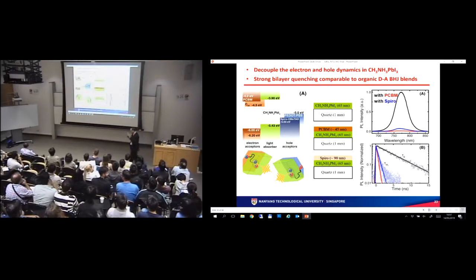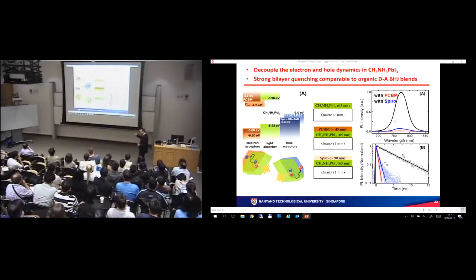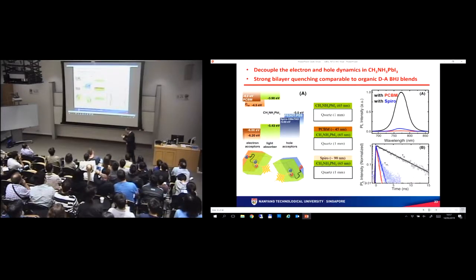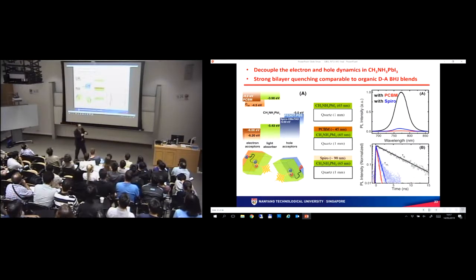After you interface them, you look at the photoluminescence. The photoluminescence suffers a big hit after you interface it with your electron or hole extraction layers. Similarly, the lifetimes decrease, and this amount of photoluminescence quenching is very significant. It's comparable to the bulk heterojunction donor-acceptor pairs that we usually work with, for example the P3HT:PCBM systems, where the donor and acceptor domains are only about 10 nanometers apart from one another. In this case, we have a bi-layer configuration with layers about 65 nanometers thick. What all this suggests is that the diffusion lengths are fairly long. Now, how long is long?